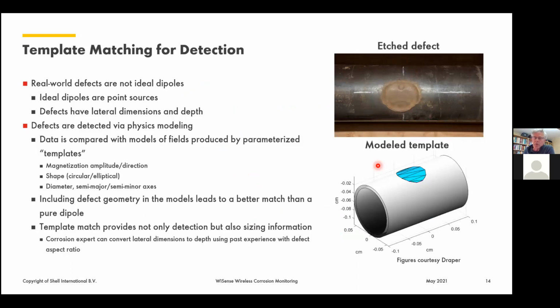What I introduced a few slides ago is that with magnetometry we try to measure dipoles, which are in fact ideal dipoles as point sources. But real defects have a certain extent. And that means that also the field generated is not the pure dipole. So we had to develop a sort of modeling, where the magnetic field is modeled as coming from an extended area. And that is then translated into what we call templates.